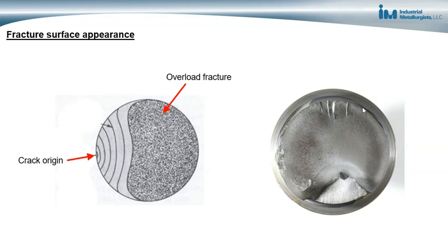And this shows a shaft that fractured during use. The crack started here and moved across the surface, and then finally this is the part that failed due to overload. So this part failed under bending fatigue loads.